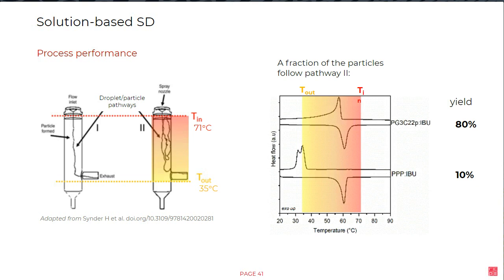Here we have a DSC analysis of PG3 with the highest yield and tripalmitin, that you remember, had very, very low yield. So all the particles reaching the inlet are going to be molten immediately, since the melting point is exactly below that. So all of them are molten. The difference between PG3 and tripalmitin is, however, their recrystallization temperature. After the particle is exposed and molten at this higher inlet temperature, it will almost immediately recrystallize, and it will have a very short residence time in the chamber in a molten state, meaning that wall deposition and product loss will be negligible.